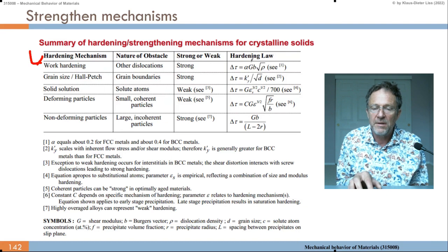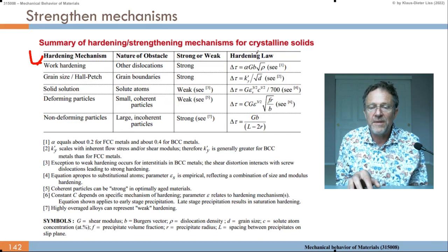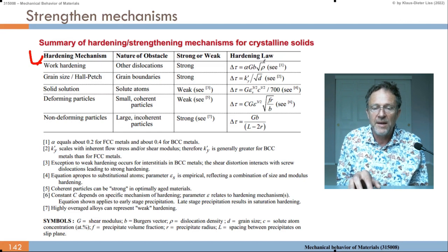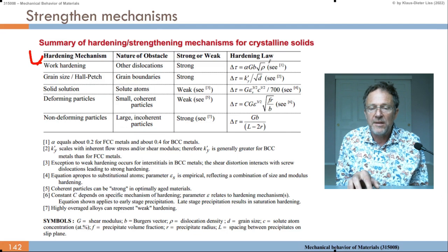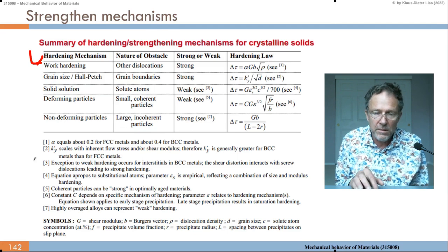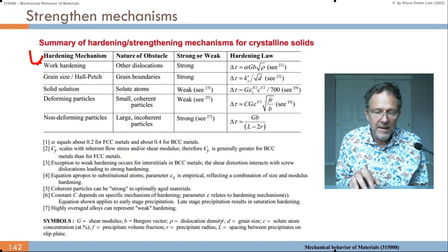Then we have the shear modulus, of course. We have the Burgers vector. For a larger Burgers vector we need a larger shear force. And then it goes with the square root of the dislocation density rho. So rho, somewhere here, is the dislocation density. You see that here.